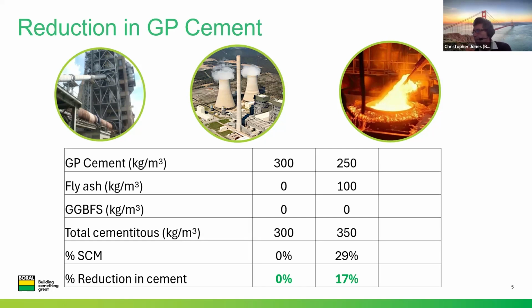This has resulted in a mix with 29% fly ash, but the GP has only been reduced by 17%. I still see specifications to specify low carbon concrete by a percent of SCM, e.g. 30% SCM. But as you can see, this will not result in a 30% reduction in GP cement when using fly ash.